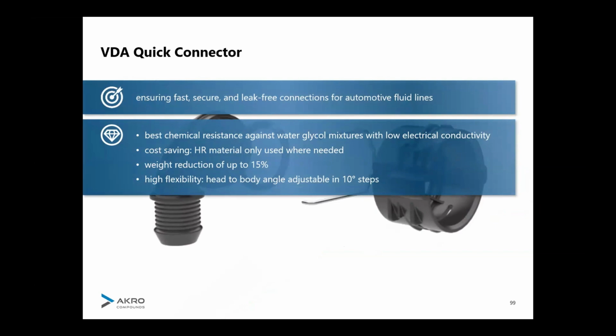And now something important comes into play, which is coming from Asia right now. Chinese battery electric OEMs use new cooling agents. They realize that if you have cooling agents which are conductive, and you have an accident and the cooling agent drops on your battery, a higher conductivity increases the risk of a fire or short circuit. So they are now going for water glycol mixtures that have very low or no electric conductivity. Now these cooling agents are more aggressive in the first step, so we need to make sure that our materials are resistant against these special cooling agents.